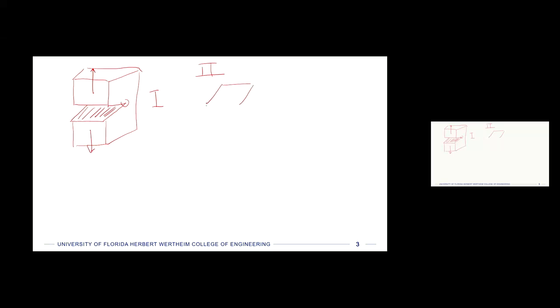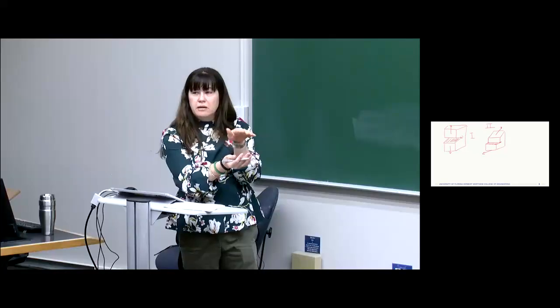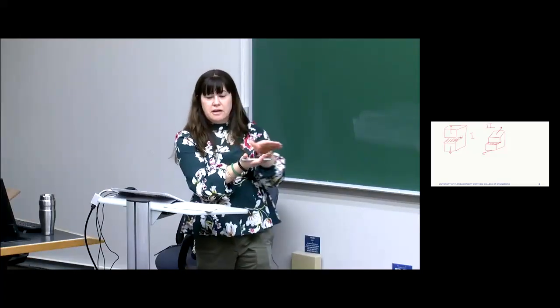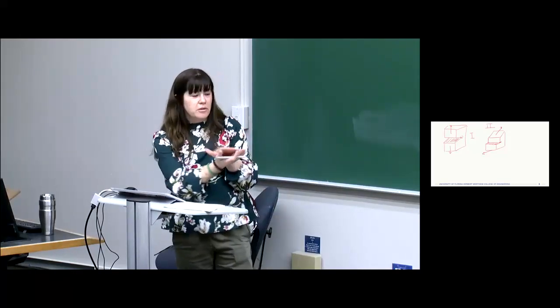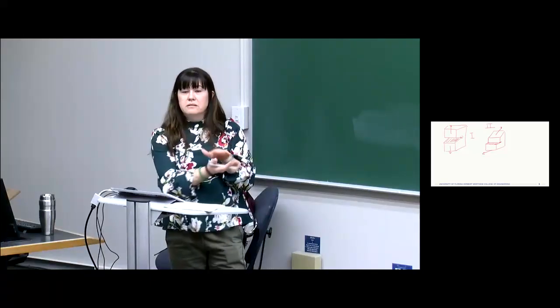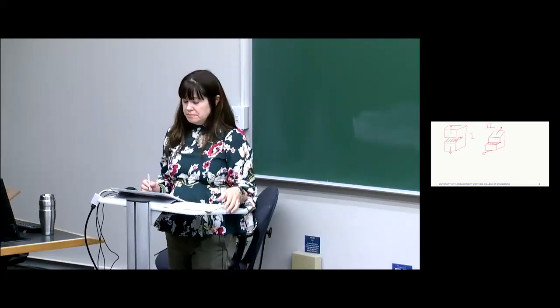All right, so let's draw it like this. And then your crack is actually forming like here, and it goes back just a little bit. And so you can imagine there's a load on the top plate pushing backward, and correspondingly on the bottom plate kind of pushing forward. And so my mental model for this is if you have a stack of playing cards and they're stacked up nicely, and then you shear the top, and if it's a nice set of playing cards, then they will all fan out. And so you're creating stair steps. And so that's mode 2 crack opening.